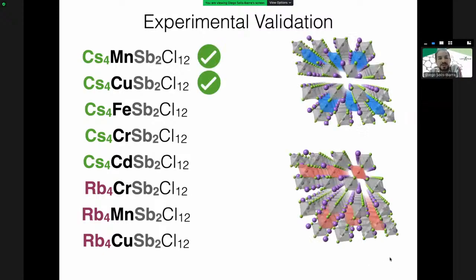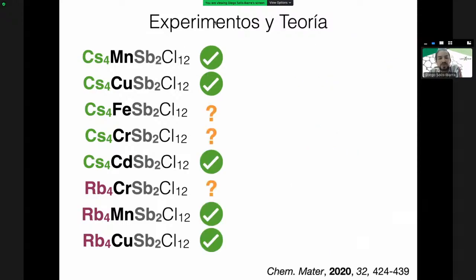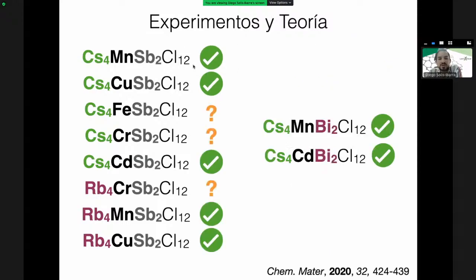And here's the list of materials that our calculations suggested are stable and we should be able to synthesize. It was nice to see that these first ones that we previously synthesized, that I already talked about, are indeed predicted to be stable. It's an important thing, that our calculations were consistent with our previous results. And then what we were able to do is to show that all these other materials that we had in synthesis before, we were able to synthesize them and prove that we can get to them experimentally, right? There's still a few that we've not been able to do.